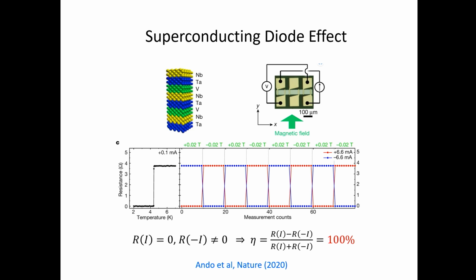Okay. So, in the last few minutes, let me switch to yet another kind of non-reciprocal effect, not in conductors, but now in superconductors. This was an experiment reported in 2020 from Japan, in an artificial superlattice of superconductors of niobium, tantalum, and vanadium. This tri-layer sandwich structure breaks inversion symmetry, and under an external applied magnetic field, it was found that the critical current is different in opposite directions.